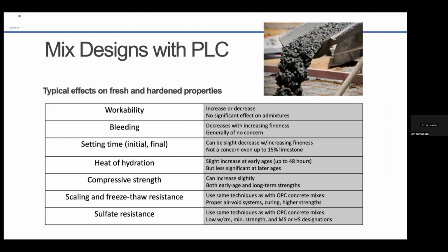So in mixed designs of PLC, workability doesn't seem to be any particular increase or decrease. Bleeding decreases with increasing fineness, generally no concern. Setting time can be a slight decrease with increasing fineness. Heat of hydration, slight increase at early ages, but less significant at later ages. Compressive strength can increase slightly, both early age and long-term strength.